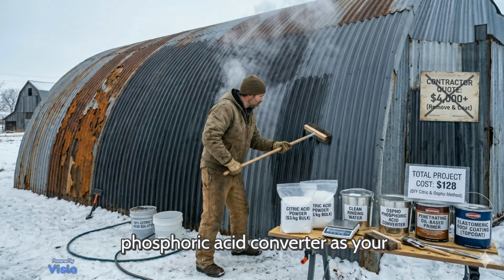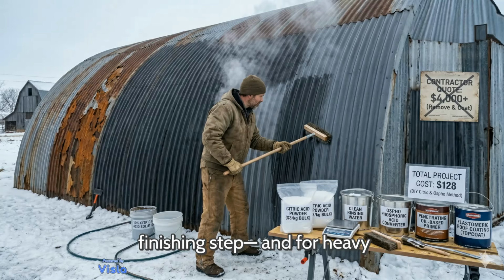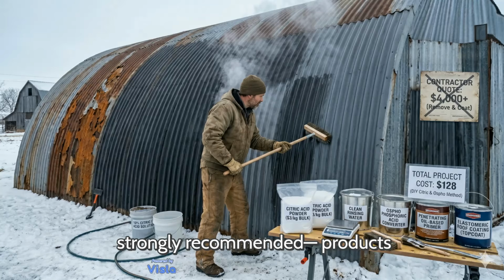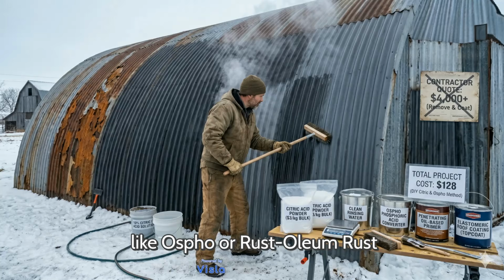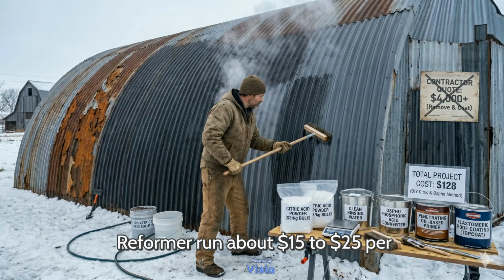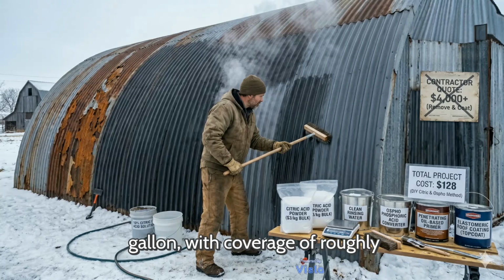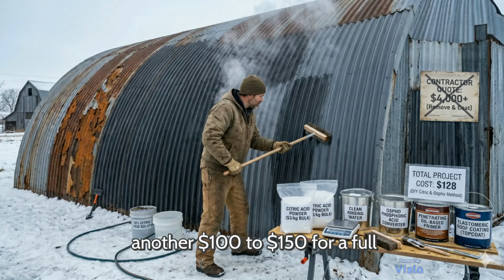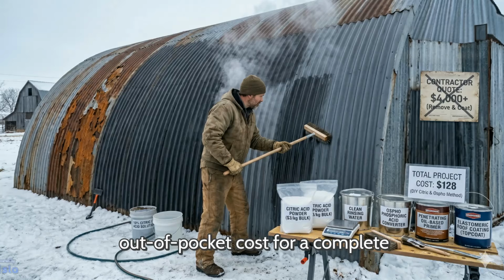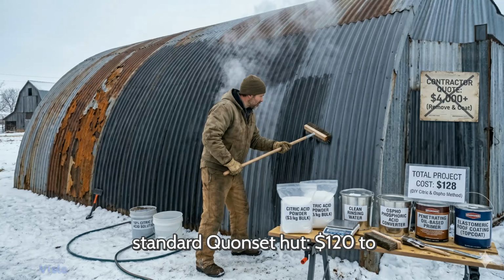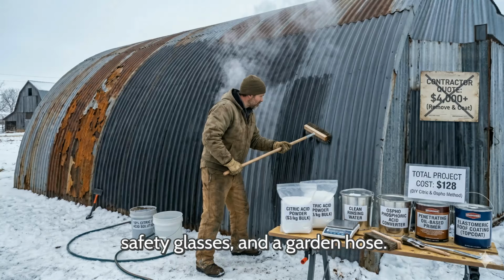If you're using a commercial phosphoric acid converter as your finishing step, and for heavy outdoor rust exposure, this is strongly recommended. Products like Ospho or Rust-Oleum Rust Reformer run about $15 to $25 per gallon, with coverage of roughly 100 to 150 square feet per gallon on corrugated surfaces. Budget another $100 to $150 for a full Quonset treatment. Total out-of-pocket cost for a complete two-stage rust conversion on a standard Quonset hut: $120 to $180. Tools required: a stiff bristle brush on a long handle, a bucket, rubber gloves, safety glasses, and a garden hose.